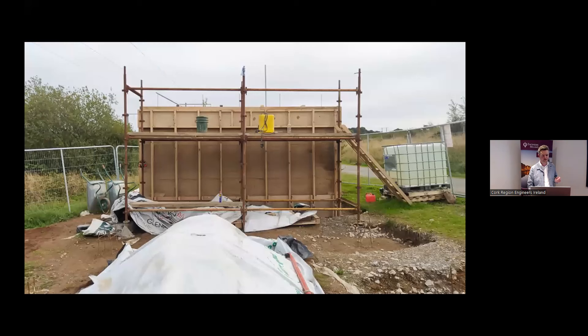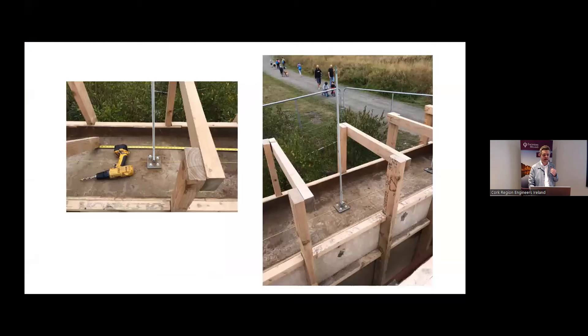There was a slight crack across the surface of the earth — this came when we brought the earth up to the final compaction layer. The earth was forming a meniscus on the former, and when we removed the form we were pulling away the top layer. We realised that every time you go up you need to cut the top layer off so it's all flush — that way when you remove the former you don't get erosion of the top surface. The white leaching visible is from the cement and carbonation. And this is the structure for the roof.